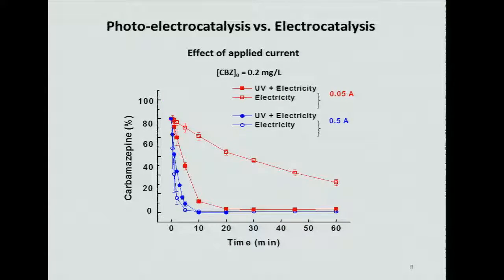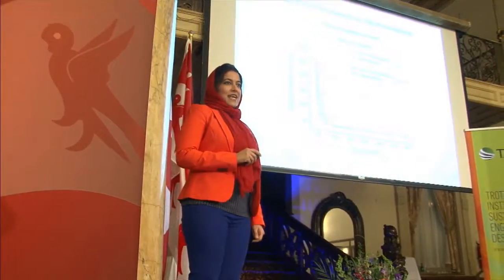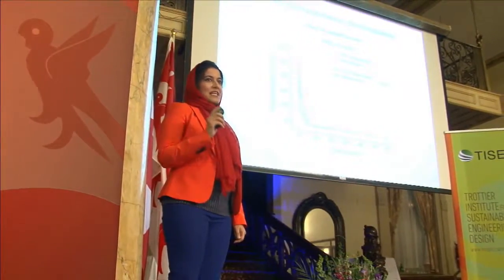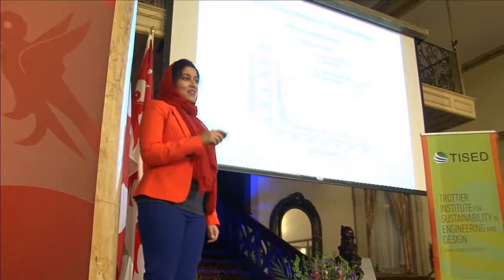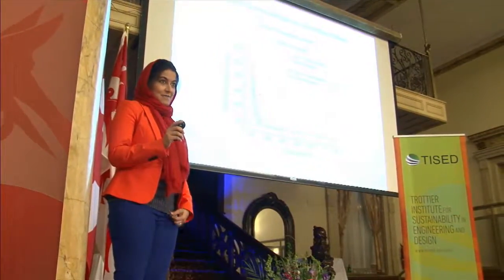If we compare the results of the electrocatalysis process with the photoelectrocatalysis process, we find out that at lower currents, the photoelectrocatalysis process worked much better for the removal of carbamazepine. But as you can see, at higher currents, both processes worked almost similarly. It indicates that UV energy plays a more important role at lower currents.